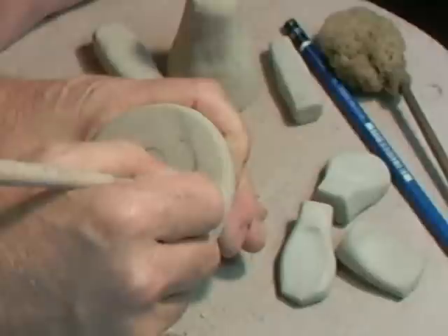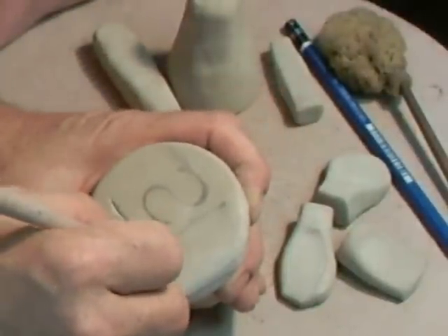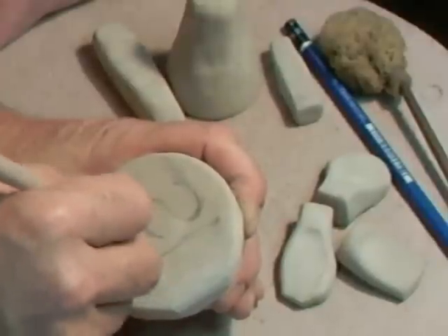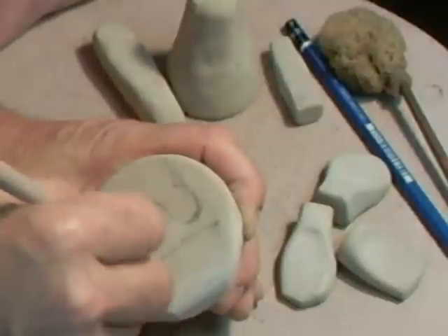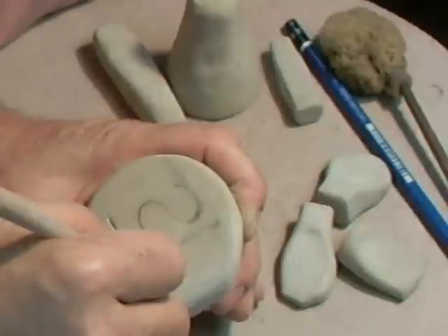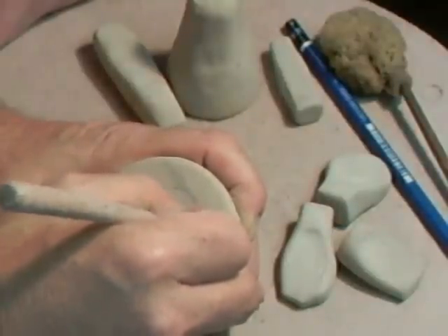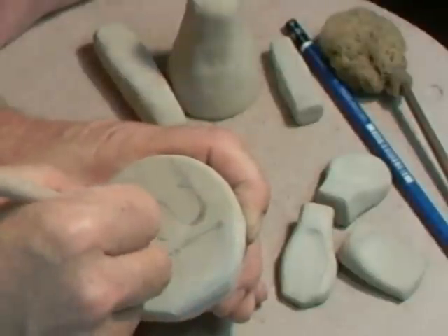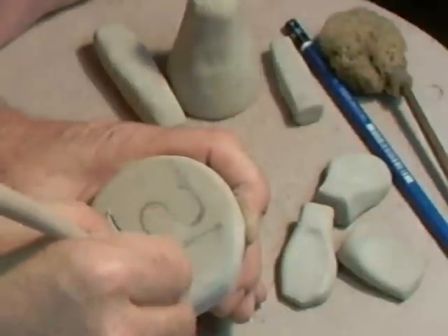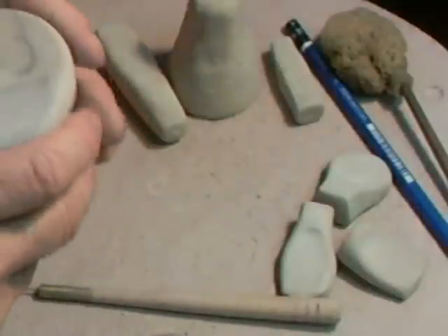Need a bit of it. And you get plaster in your clay, which I have had. Terrible business. When I was out in Spain, I used to get the clay supplied from the supplier. It used to have lime already in the clay. I think they put it in on purpose. I went down to the clay supplier with a box load of pots with all wood blowouts on them from bits of lime in the clay.